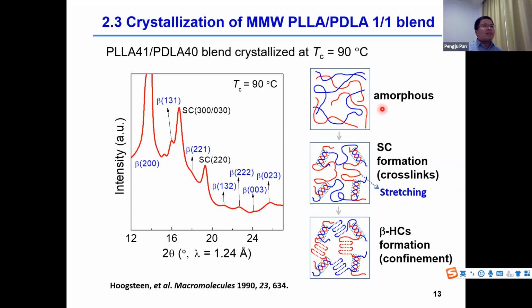In the crystallization process of the medium molecular weight blend, a high content of stereocomplex crystal is first formed. This stereocomplex crystal can work as a cross-linker and retard the regular packing of polymer chains in the following crystallization process. The cross-linking effect of stereocomplex can have a stretching effect on the polymer chain and induce the formation of the beta homocrystal with a more extended polymer conformation.